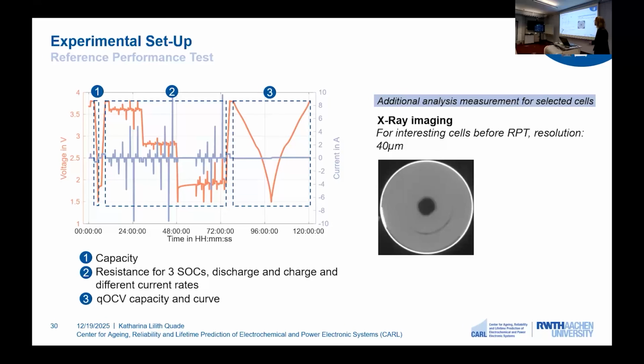And last but not least, we can also see that we are conducting so-called quasi-open circuit voltage measurements where we charge and discharge the cell with a very low current. And here on the right-hand side, we can see that we are also performing additional measurements, for example, CT images. We do this for interesting cells, not for all the cells during every RPT, but we do this if we see any irregularities in our electrical data.